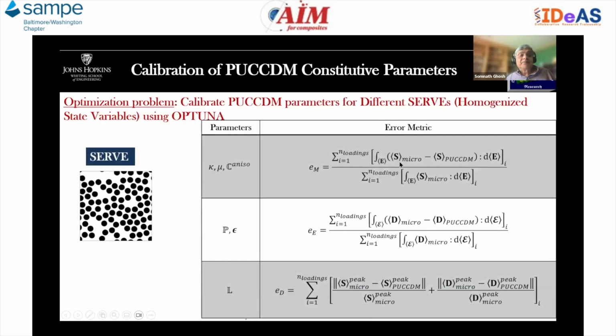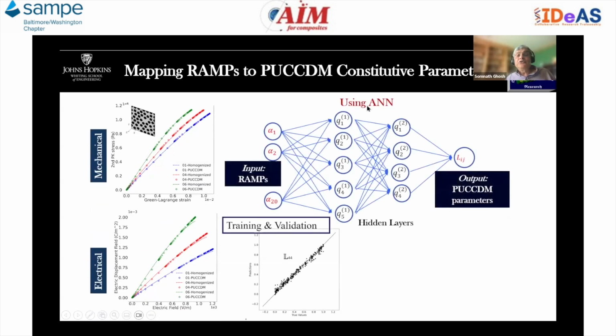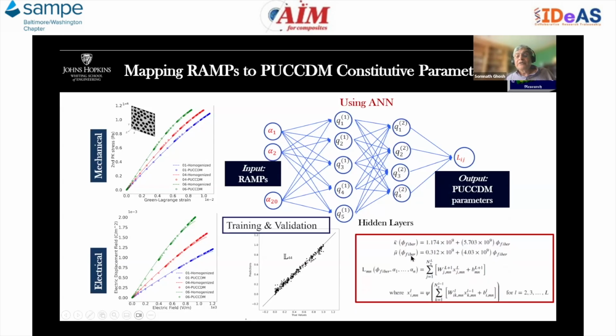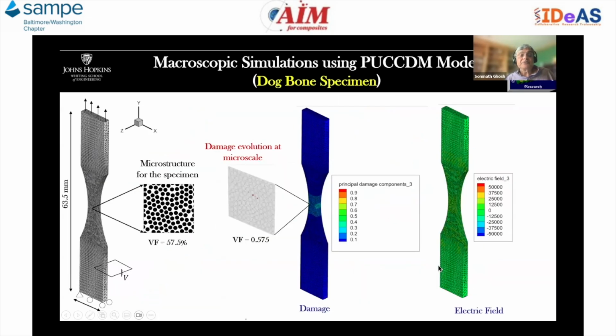To do that, there's a two-step process. First, we set up the PUCCDM parameters from the MRDB using the code Optuna. Here we are minimizing the error in the macroscopic load, the electric load, as well as the damage evolution. And then once we have that, we use an artificial neural network to come up with a representation of those various PUCCDM parameters in terms of the underlying microstructural RAMPs. This corresponds to the fiber volume fraction, and this W is a function of the principal components representing the distributions.